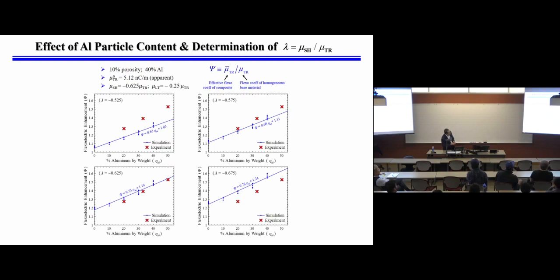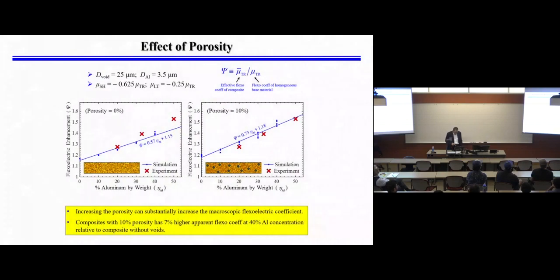So computationally, what we can do is systematically analyze the ratio between the flexoelectric coefficients, how much each gradient would contribute. We can systematically do that. And what we found is that they must have roughly this ratio, 0.625 with the negative sign. That would really explain the experimental trend. And this is something that experiments cannot do, but computations can do. So using the microstructure simulations, we can back out individual coefficients that can then be used to do more systematic simulations.